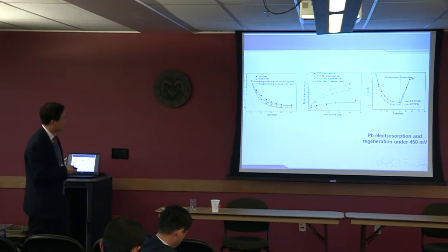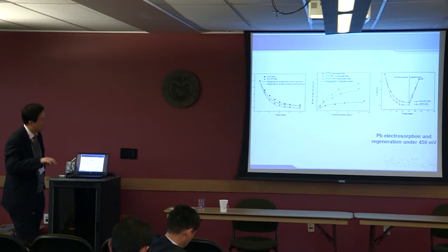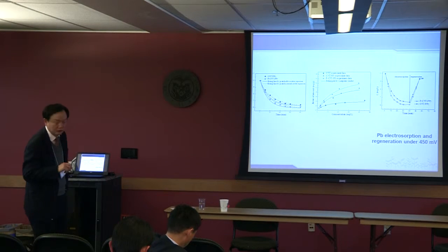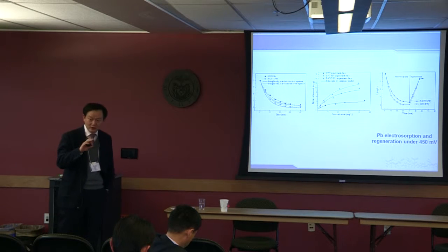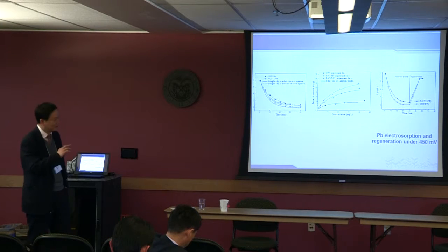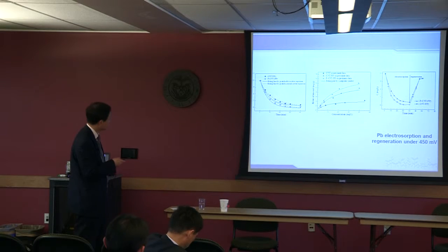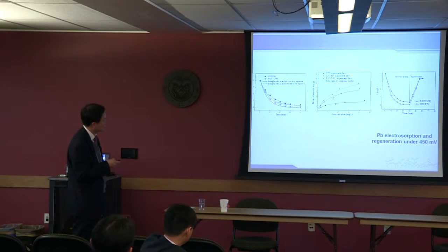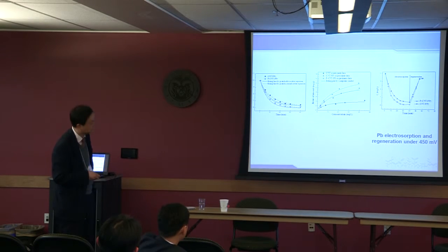Here's the result. We measured the residual concentration of the metal ions. We chose lead as the model ions for the experiment, and the result showed, see here, the starting solution. As time goes on, the concentration of lead in the remaining solution decreases fast.